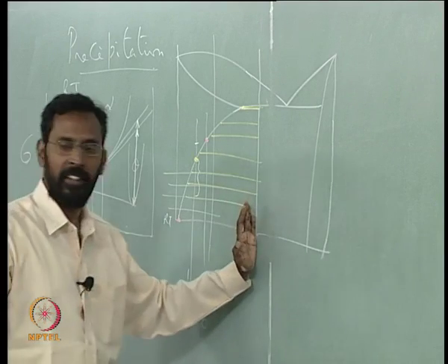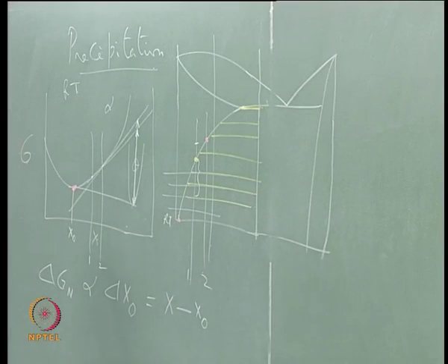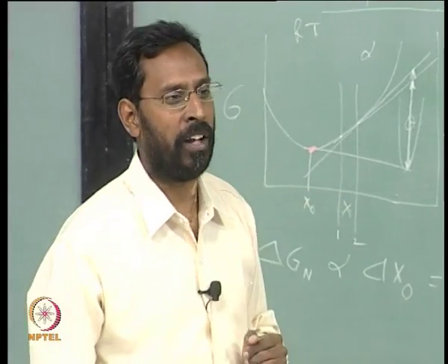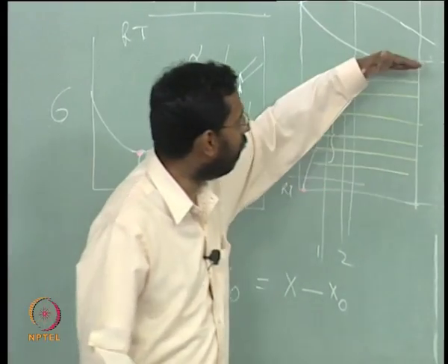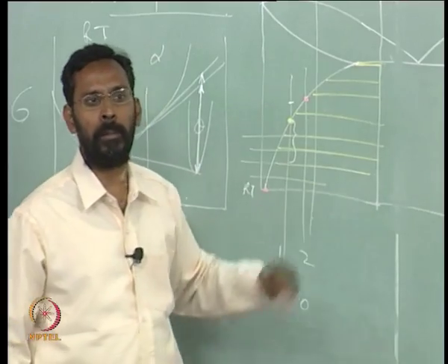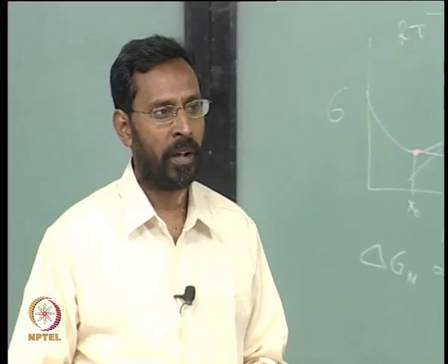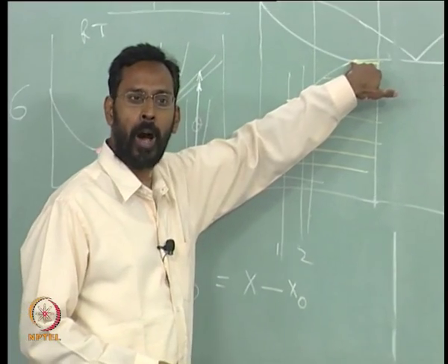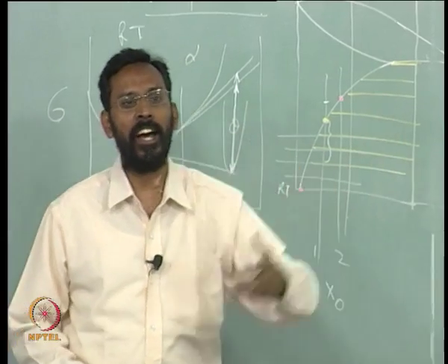Whereas, in this alloy, the theta does not come out by precipitation from the alpha, it comes out as a eutectic mixture. But you can still ask me, sir, after the eutectic reaction, when I cool it from the eutectic temperature to room temperature, what is supposed to happen? After solidification is completed, but the solid is now cooling to room temperature, should anything happen in that alloy? The theta should increase. Why should it increase? Because the solubility of copper in alpha is decreasing, and where should that increased theta appear?